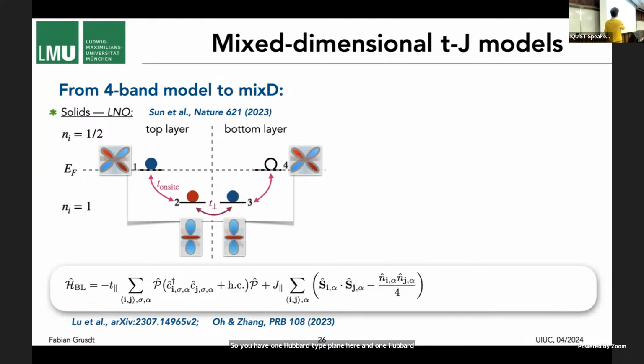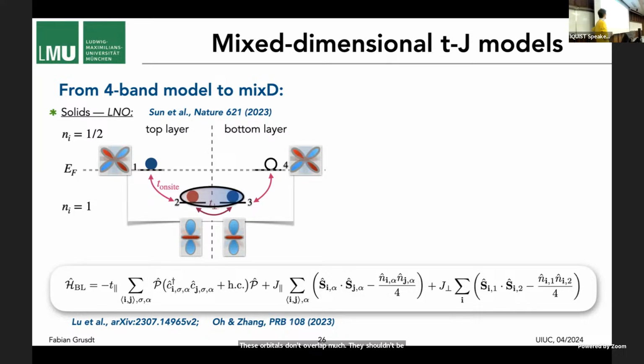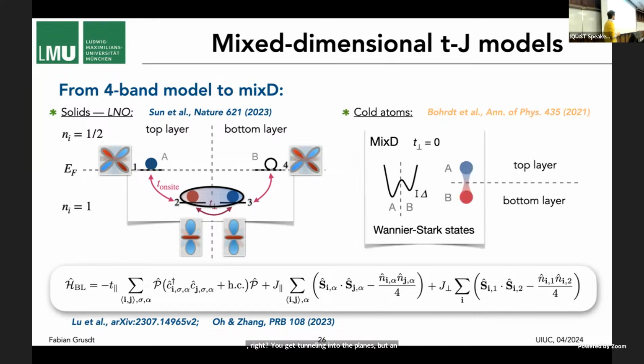Now, the point is, there's no tunneling. These orbitals don't overlap much. There shouldn't be much tunneling, but they couple to these energetically lower lying orbitals. And in here, you have a strong antiferromagnetic super exchange interaction. And what this can do is, even if these guys are kind of just sitting there, just watching, right, they can mediate an antiferromagnetic super exchange interaction between the physics layers. And that's exactly what you need to get a mixed-D system, right? You get tunneling in the planes, but an antiferromagnetic super exchange between these two layers. And again, this is the trick that they played in cold atoms to realize this.